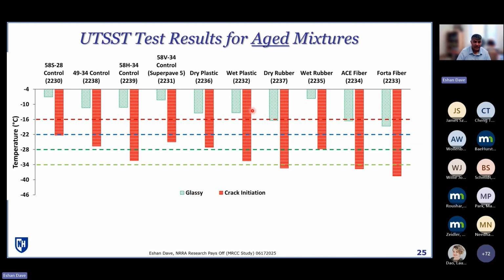Now, all the results here are for aged mixtures only. So the green and red doesn't mean short-term or long-term age. Green is just the glassy temperature. Red is the crack initiation temperature. Just to make it clear, I put the grade lines. Those are your standard Superpave PG low temperature grade lines at minus 16 and then 6 degrees thereafter.